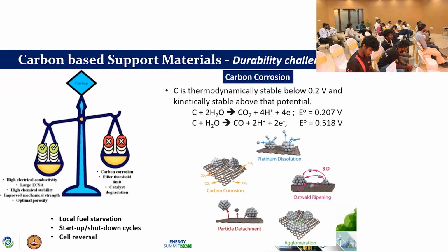This carbon corrosion basically happens due to the oxidative corrosion of carbon. Carbon in various forms is thermodynamically stable below 0.2 volts and kinetically stable above that potential, which means that above this potential it will become thermodynamically unstable and will try to undergo oxidation. It will react with water, forming either carbon dioxide or carbon monoxide. That is one disadvantage, and it will eventually end up in issues like platinum dissolution from the support materials, Ostwald ripening, agglomeration and so on. In some cases, the electrocatalyst particles themselves will detach from the support materials due to carbon corrosion. This will generally occur because of local fuel starvation, startup-shutdown cycles or cell reversal processes.